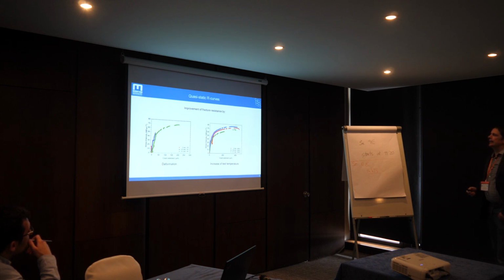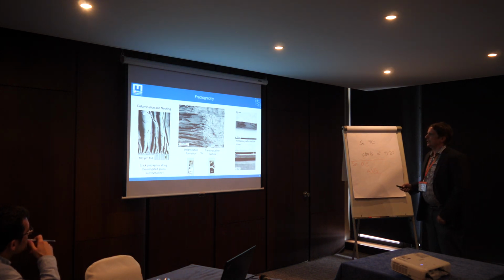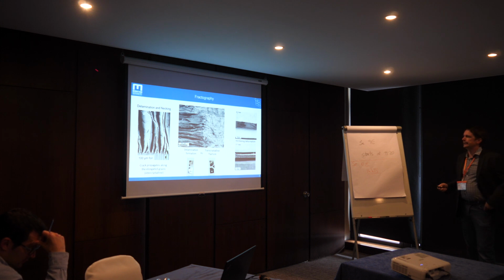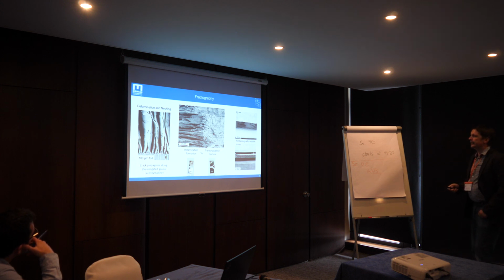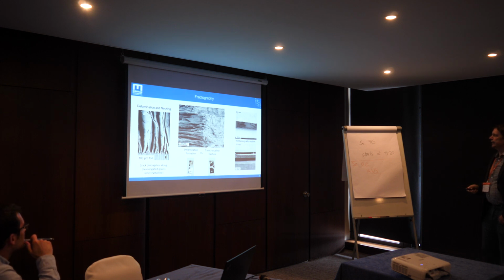And the reason for this you can find on the fracture surface. You get here such delaminations, which will change the stress state at the crack front from plane strain to plane stress. And in addition, we also have strong necking of the remaining ligaments. And in competition to this delamination formation, we also get transcrystalline fracture in the samples, which propagates approximately under 45 degrees with respect to the pre-crack. And with increasing deformation, the area of these delaminations becomes larger and the R-curve behavior becomes more pronounced.